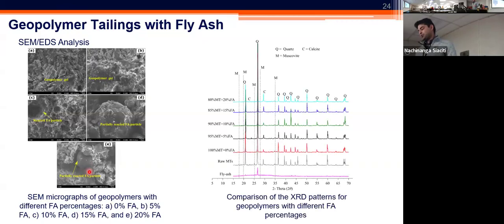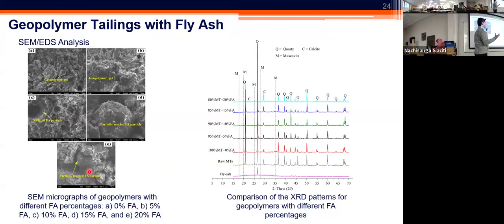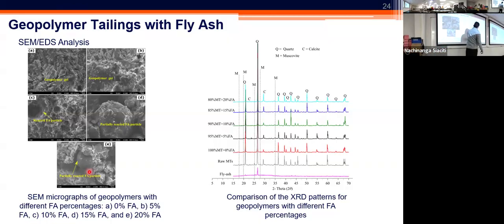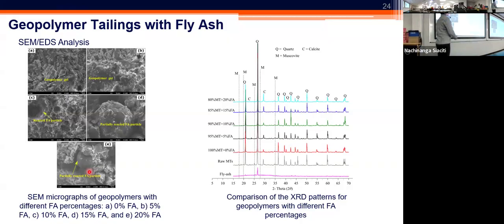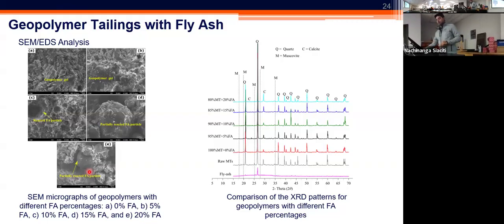We then looked into the XRD to identify some evidence of sufficient and successful geopolymerization. One of the first things that we saw from the XRD patterns was a general trend of reduction in the intensity of the quartz, or silicon dioxide. These intensities started to decrease as the percentage of the fly ash increased. So the first evidence was that this is a good sign that some of the existing quartz otherwise observed in the original raw mine tailings was being consumed and participated in the geopolymerization. We also saw, at 2 theta of about 28, the peak for the calcite intensifying. So we saw increasing calcite presence as a result of this geopolymerization. We took those two evidences as indicators of successful geopolymerization for these materials.